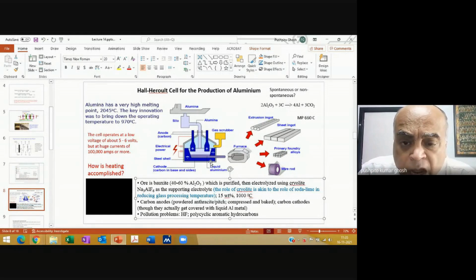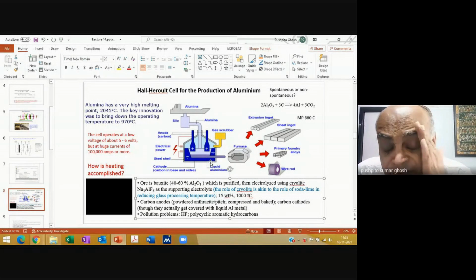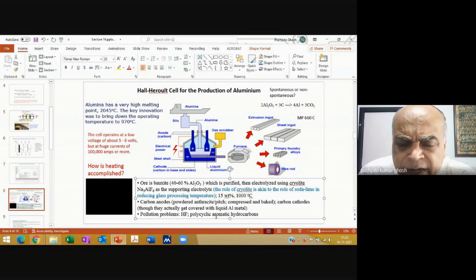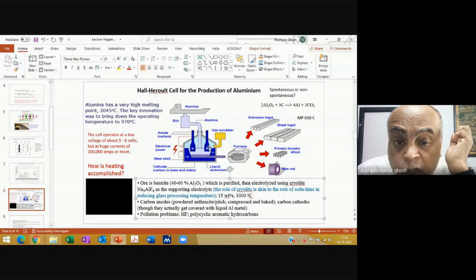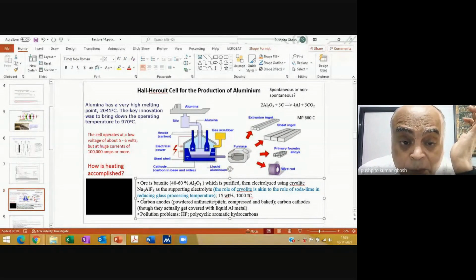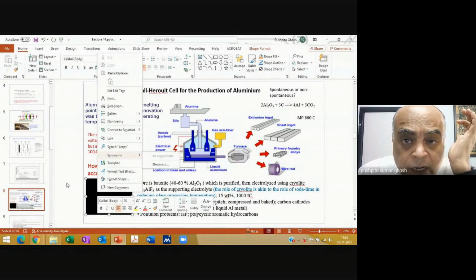So, for example, my carbon, I might form other forms of carbon through an oxidation process. Cryolite has got fluoride in it, Na3AlF6. What can happen is that that fluoride can become fluorine at the anode, and then strip off hydrogen from my pitch blend, because my pitch blend is what? It's not absolutely pure carbon. There is some hydrogen. So obviously the fluorine will react with the hydrogen, and I may get release of things like HF. So there can be competing reactions which I have to take care of. So I need a gas scrubber before I let things out, because there are volatiles, and you'll see even aluminium fluoride is volatile under those conditions, and some amount of aluminium fluoride is lost in the process. Also keep that in mind.